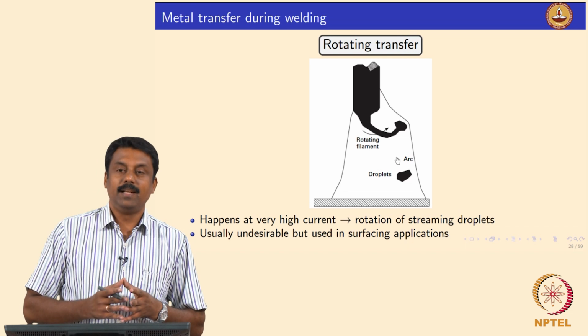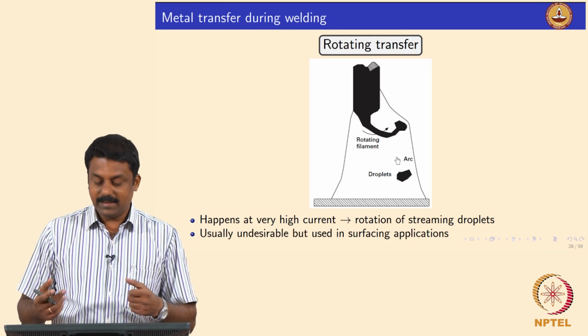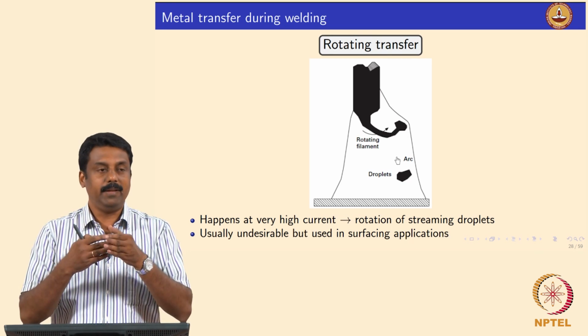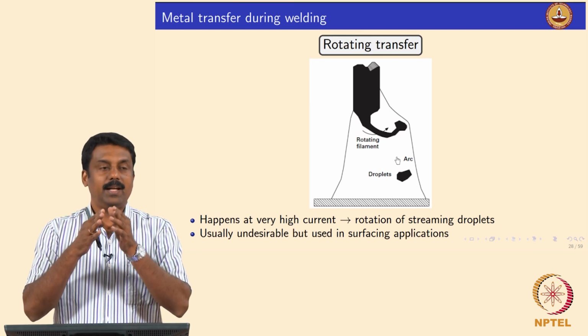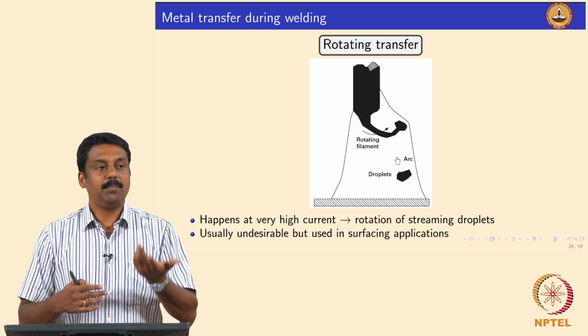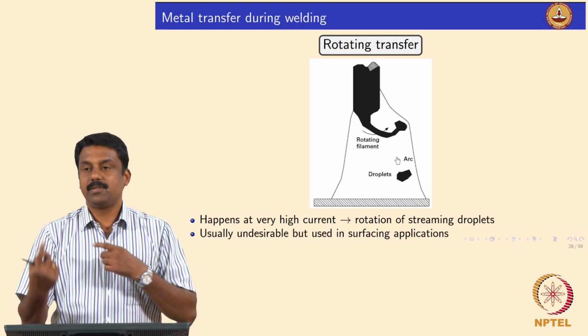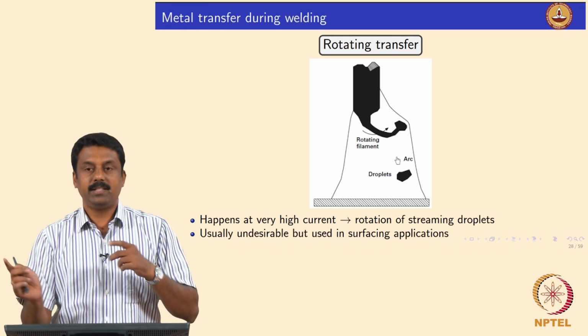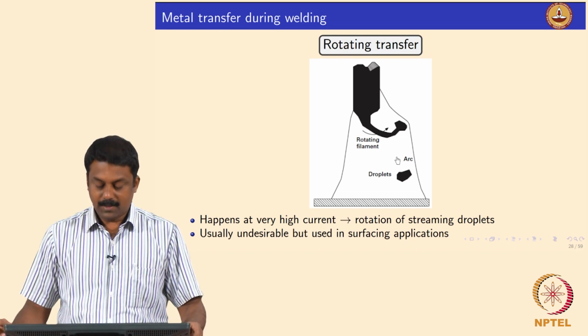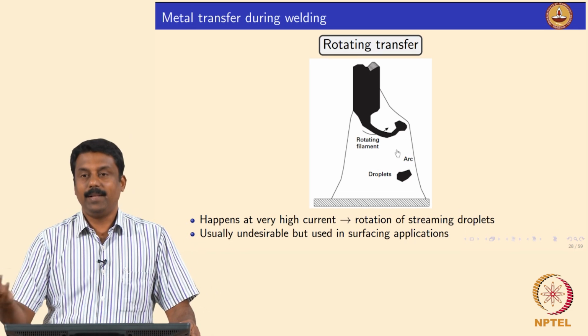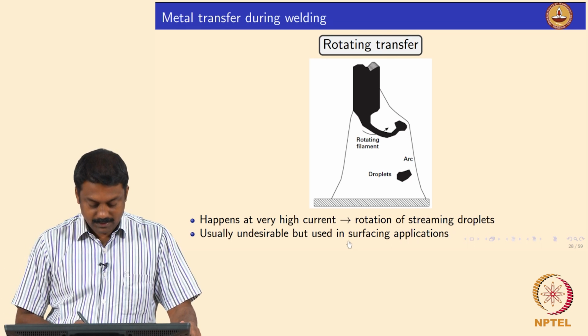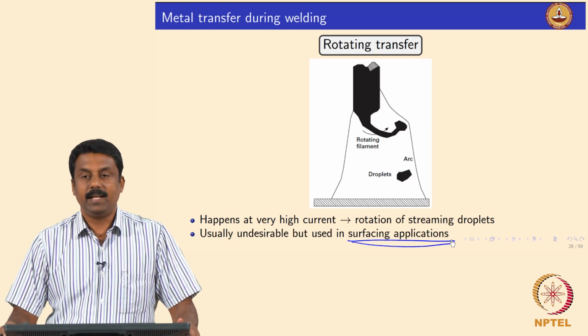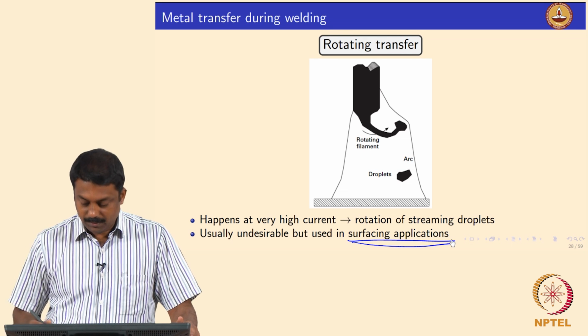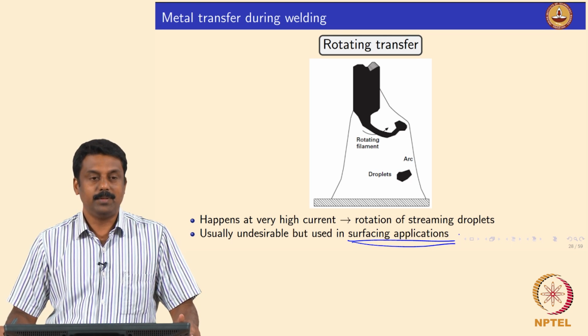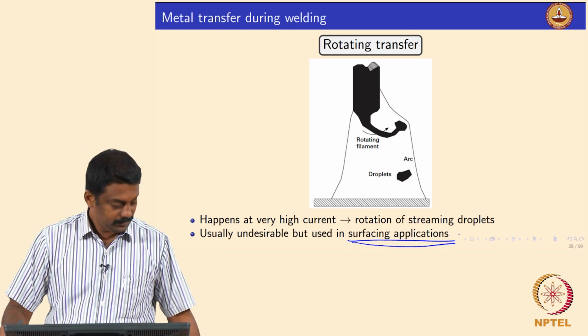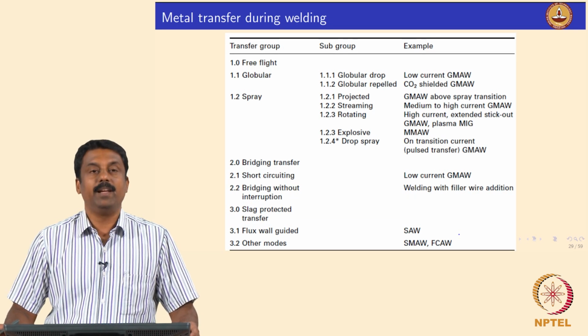If you sometimes increase the current, a jetting spray becomes rotating transfer, for the same reasons I told you. If you start making a jet and you have a Lorentz force continuously forming, certain magnetic forces start rotating or changing the path of the spray, and you will have a rotating spray transfer. It goes everywhere, and you end up transferring the droplets at various places. Again, this is also sometimes used for surfacing, using FCAW or GMAW surfacing. For welding applications it is not advisable, right. It's clear. Good.